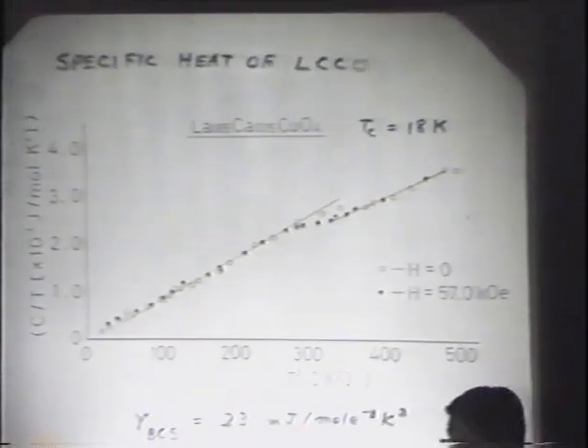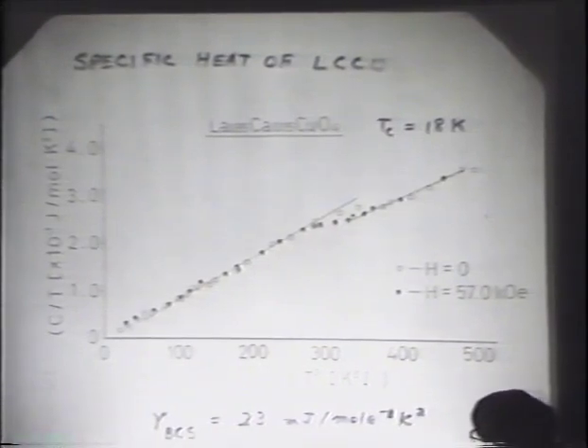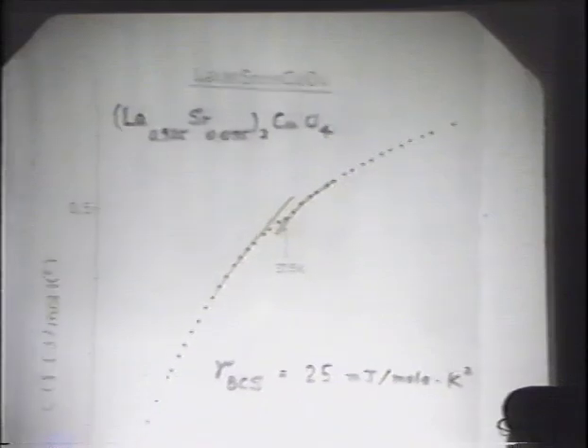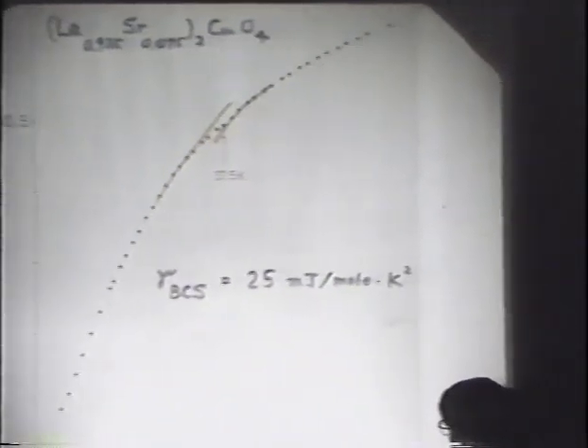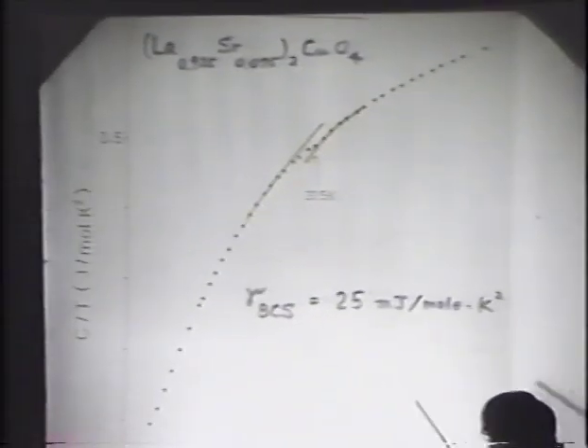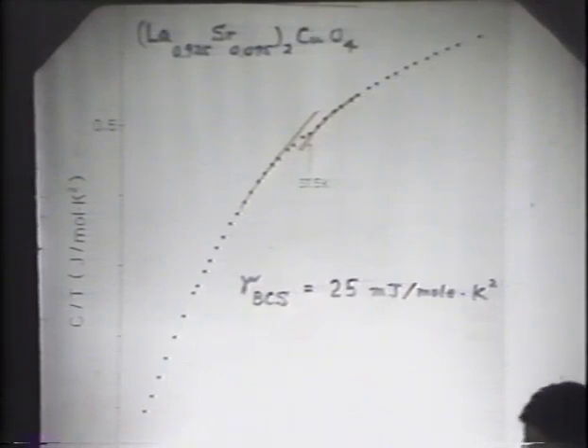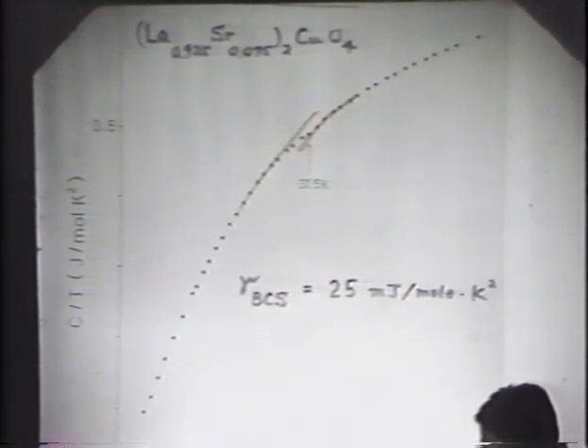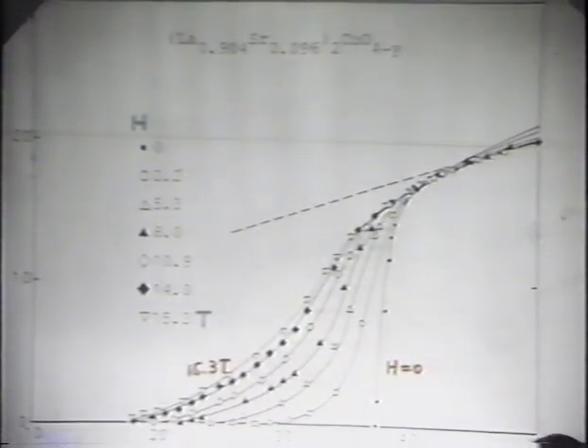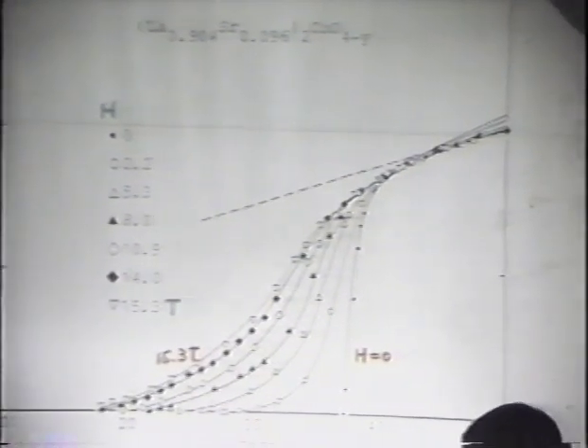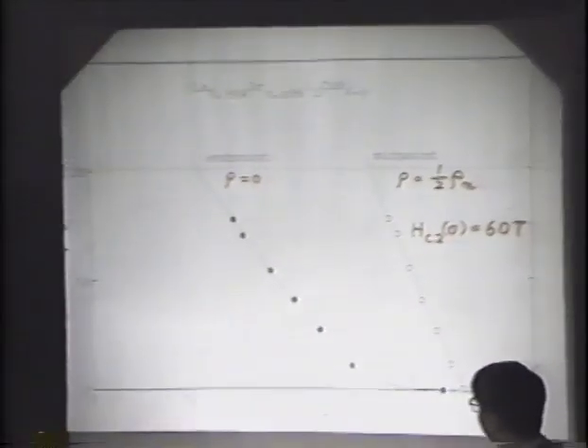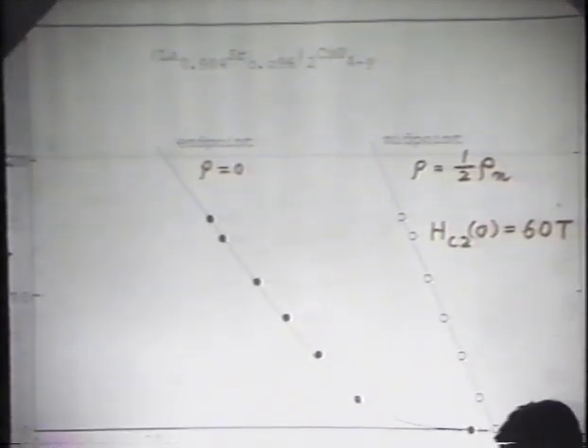And heat capacities. These data indicate a large density of states. This is lanthanum calcium copper 4. The next one is lanthanum strontium copper 4. And gamma BCS is quite large. And the effect of high magnetic field. Temperature dependence of the conductivity in a high static magnetic field. HC2 is estimated to be 60 Tesla. Summarizing the data, finally we make a tentative list of normal physical parameters and superconducting parameters.